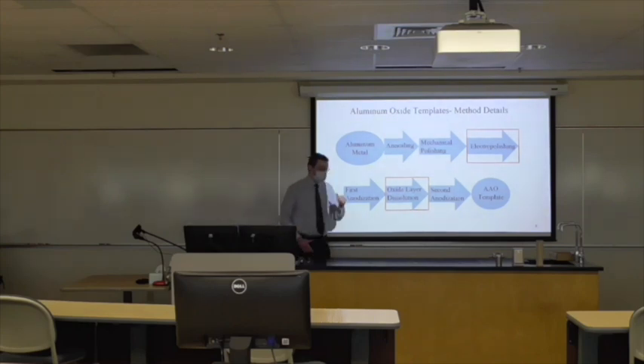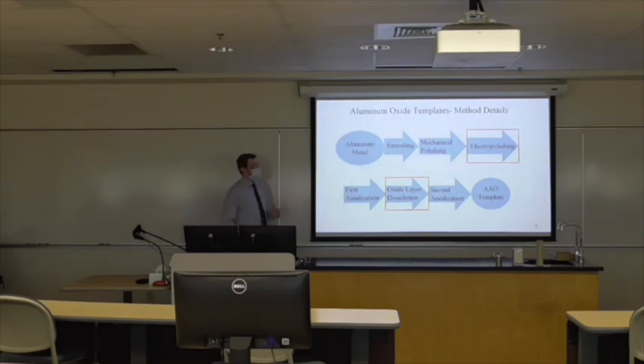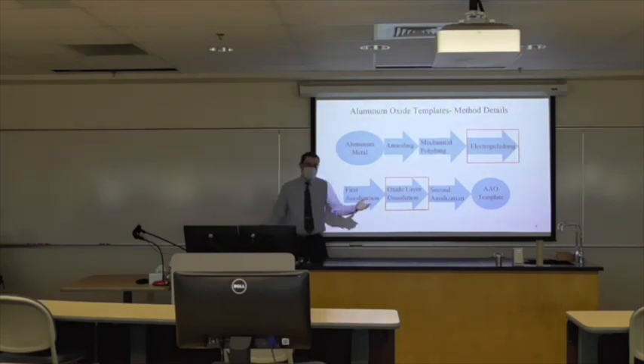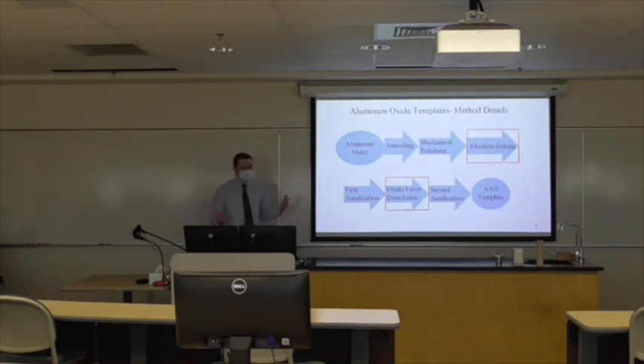So electropolishing of aluminum is generally and ideally done using perchloric acid at lower temperatures. Perchloric acid is an environmental concern, but it is also a safety concern. And you could see that partially from how we don't use perchloric acid here. We don't have a hood for it. We also just don't have the means to use perchloric acid. Perchloric acid can be explosive, depending on how it's used, and is generally not fun to deal with. So perchloric acid does really well electropolishing aluminum, but has obvious issues with it.